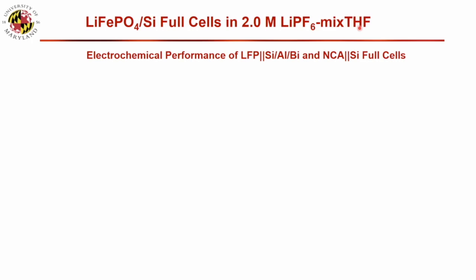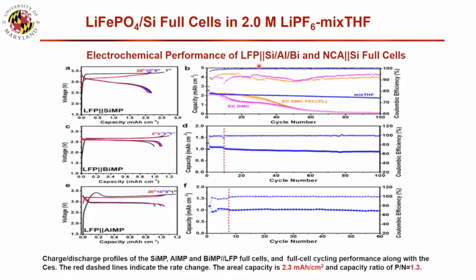THF, the problem is the anodic stability is lower because it's easier. We want to reduce the reduction potential, but we sacrifice oxidation potential, also lower. So we first try the lithium iron phosphate. We use LFP silicon matched with the bismuth and aluminum, all three, they make the full cell cycle really stable. So the N/P ratio is only 1.3.